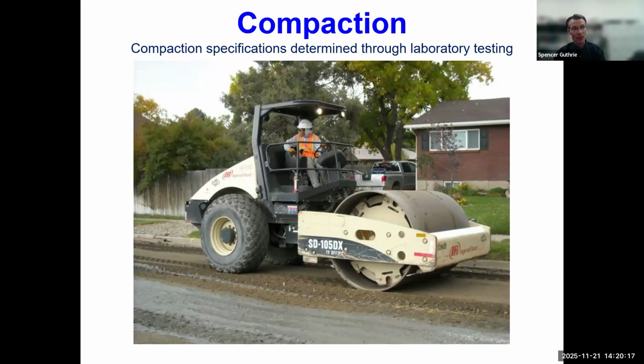I've got a note at the top. Compaction specs are determined through lab testing. Of course, we determine the maximum dry density, and then we often use nuclear density gauges to measure density very soon after compaction. And we can also measure stiffness. There are a lot of ways to assure the quality of this compacted, cement-treated, reclaimed layer.